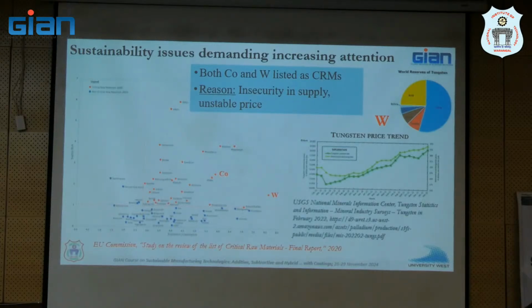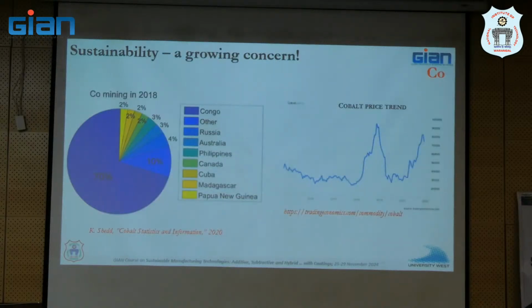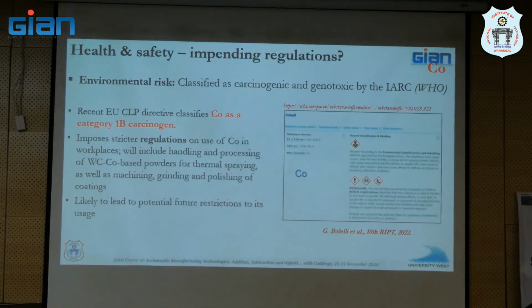Let's look at other problems with tungsten and cobalt, right? Both of them are fairly high on what is called the critical raw materials list in the EU. We spoke a little bit about that. More than 50% of tungsten comes from China, and that's not nice, right? If you look at cobalt, it's even worse. Almost 70% of cobalt comes from a tiny African country called Congo, and this is a bad situation to be in, correct? On top of that, cobalt has all sorts of health issues associated with it. So you don't like cobalt, you don't like tungsten either, but tungsten carbide cobalt is used in large tonnages by the industry today to solve their problems of wear, right?